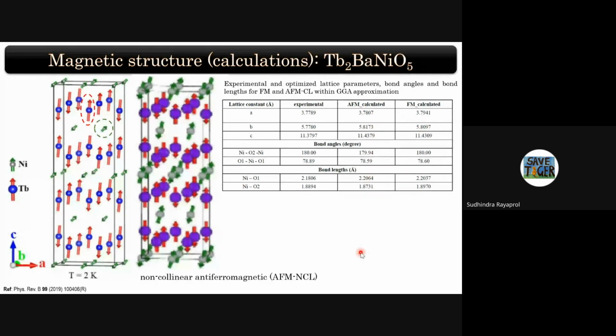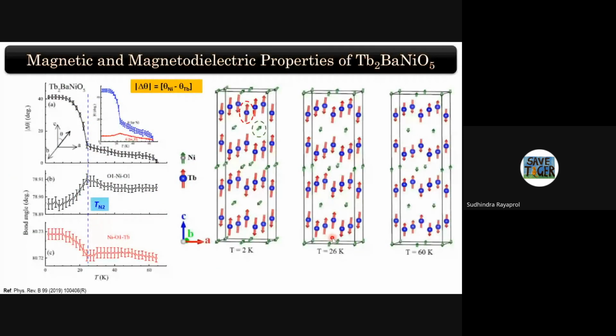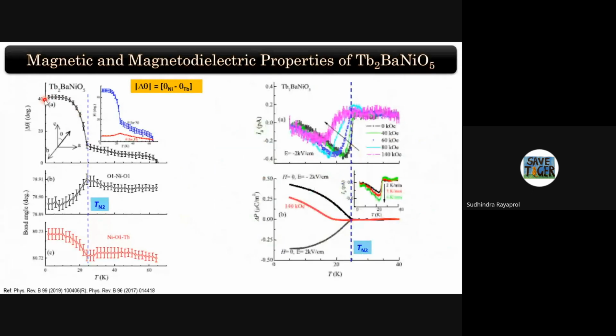and you can get parameters similar to the experiments. And what we see is that because of this critical canting angle, which is the difference between the canting angles of terbium and nickel, around 25 Kelvin, below this 25 Kelvin only, we see a huge jump in the canting angle. Because in this region only, we find that the system shows large polarization.